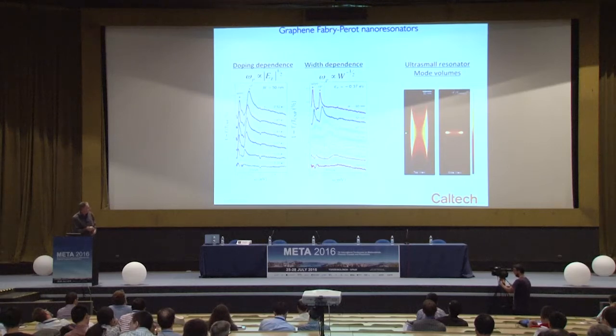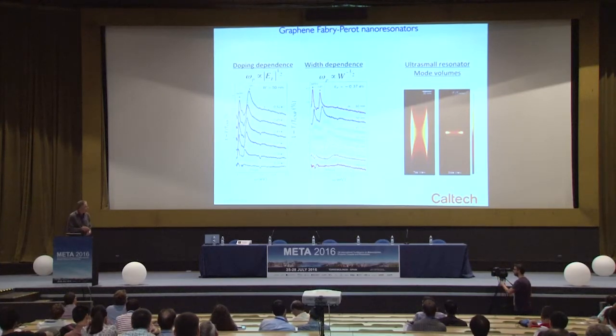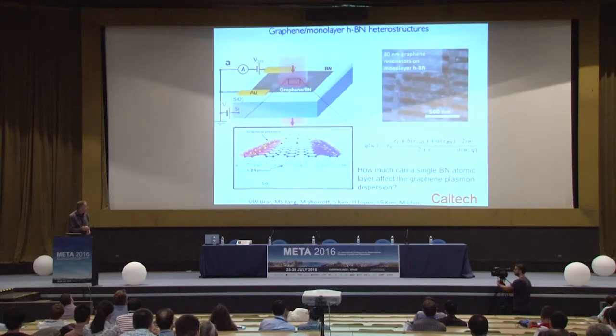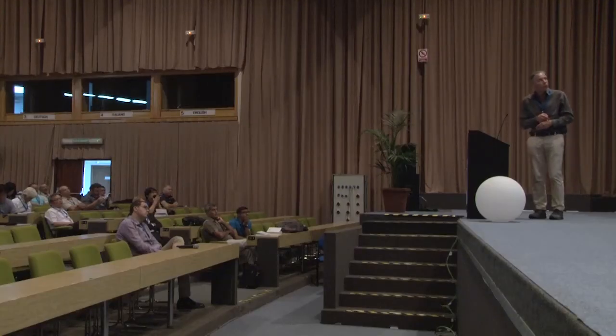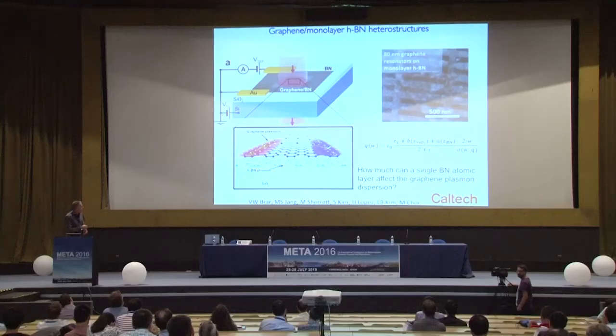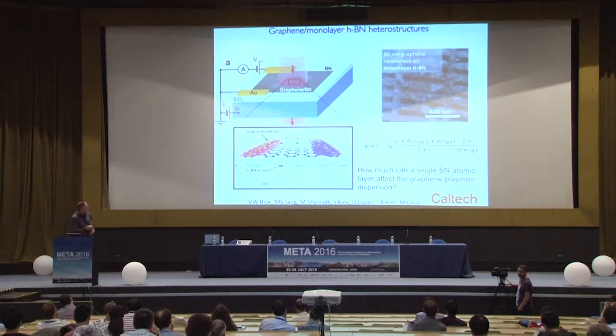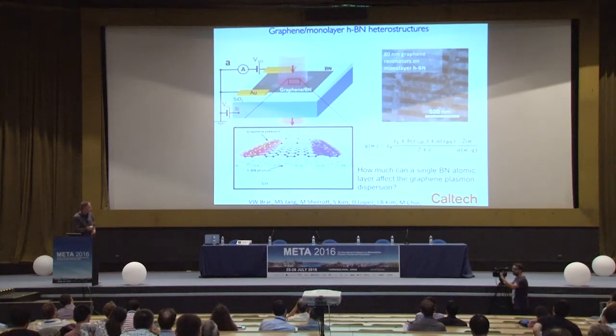And the electric dipole modes are depicted here in a simple full wave simulation. And you can see they're extremely confined within a few nanometers of the graphene ribbons themselves. And that tight mode confinement means that the graphene ribbon can couple extremely strongly to its environment. So for example, if we put these graphene nanoresonators in contact with a monolayer film of boron nitride, we can see extremely strong coupling of the graphene plasmon to the phonon polariton that is excited in monolayer boron nitride.